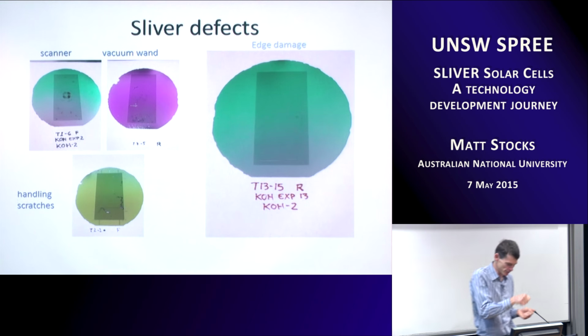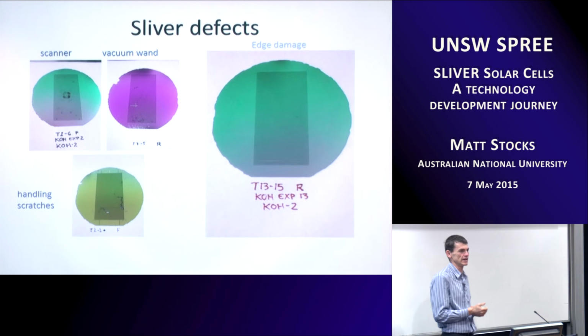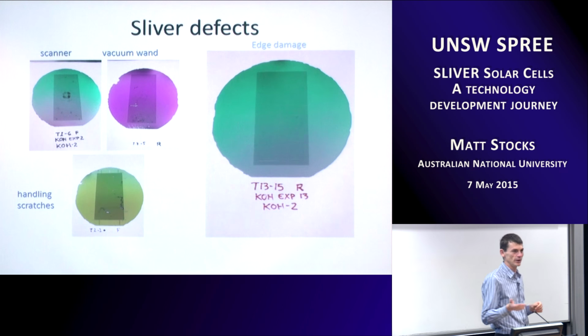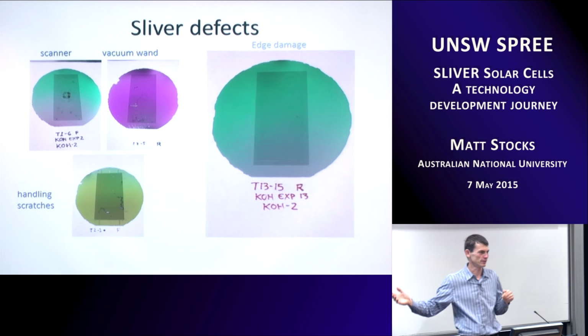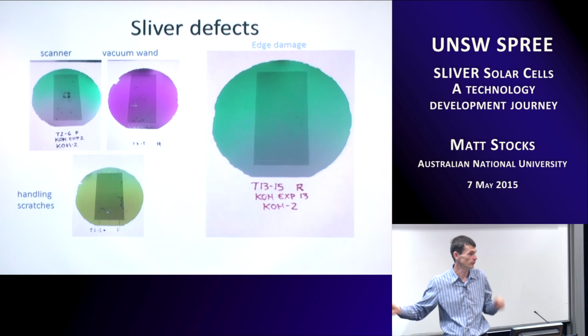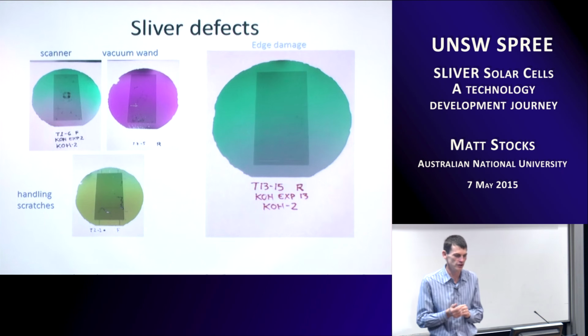You slide it in and just nicely take the edge of one wafer and drag it down the side of the other wafer, and you get these great scratches across the wafers. And of course we then stick them in KOH etching for a long period of time, and we take what looks like you can't see the scratch at all to suddenly it just blows out the entire wafer.